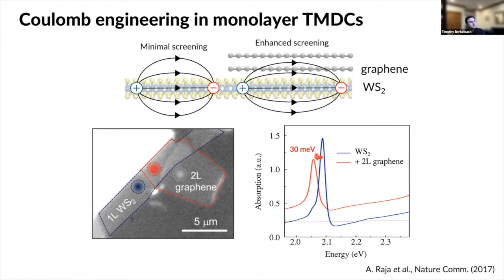The experiment compared measured spectra for a single layer of tungsten disulfide versus tungsten disulfide covered by two layers of graphene. The blue spectrum is regular tungsten disulfide with very strong peaks at the onset of absorption — clearly excitons are important. When capped by graphene there is a shift in the spectrum, providing proof of concept that the spectrum is modified just by a few atoms' worth of nearby material. The magnitude of the shift is 30 millielectron volts, which at the time we thought was kind of small. This set my graduate student Young-Soo Cho on the goal of developing a quantitative theory predicting what magnitude of change one should expect when modifying the dielectric environment of atomically thin materials.